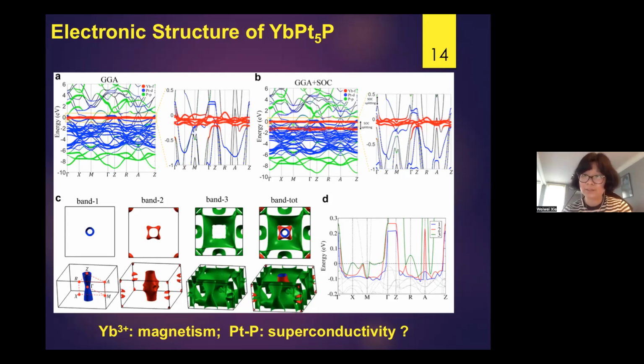But the thing is, we did the whole system from holmium to lutetium to ytterbium to yttrium, but only for ytterbium did we see the superconductivity signal. So that makes me kind of curious, because if we try to explain the superconductivity as coming from the platinum with phosphorus, if it works for ytterbium, why is it not working for the others? So it's not very convincing.